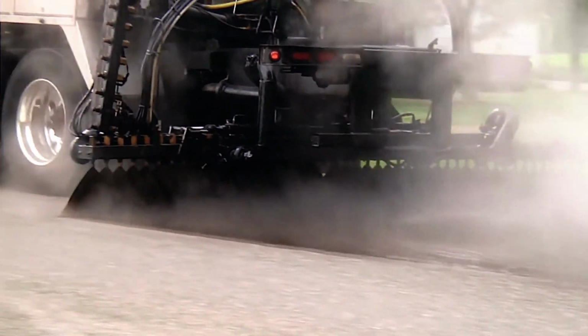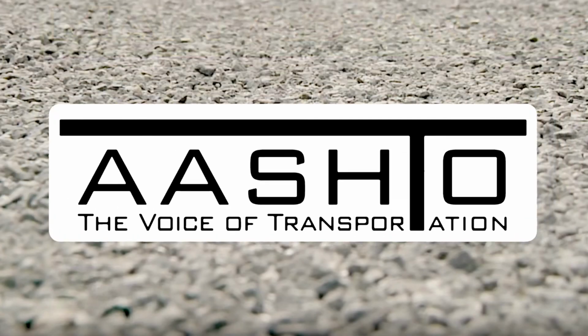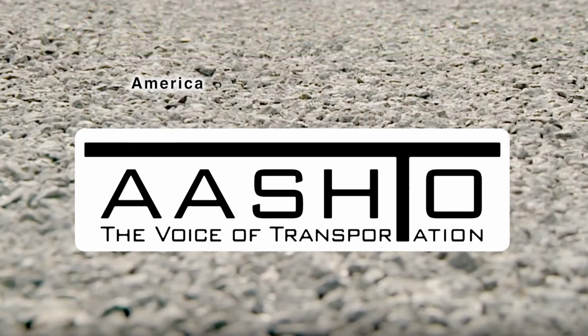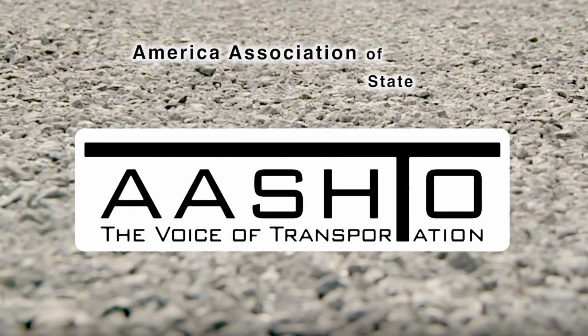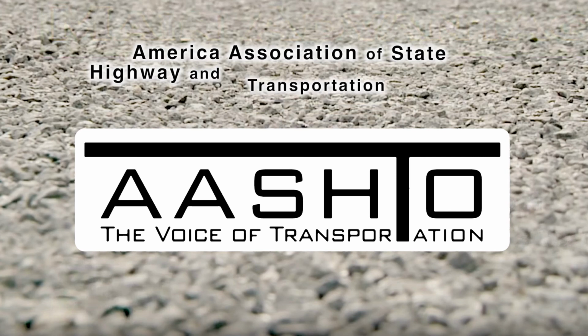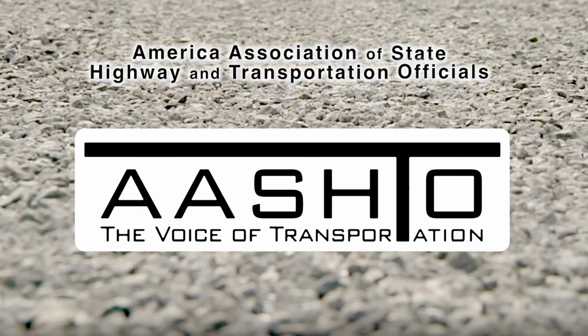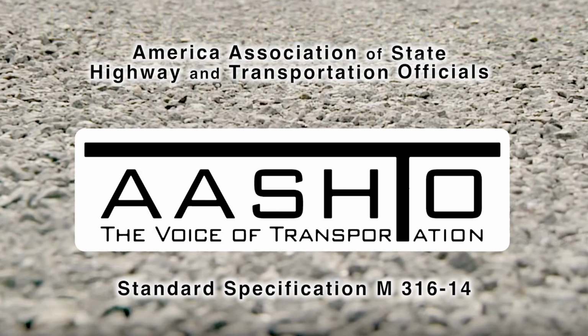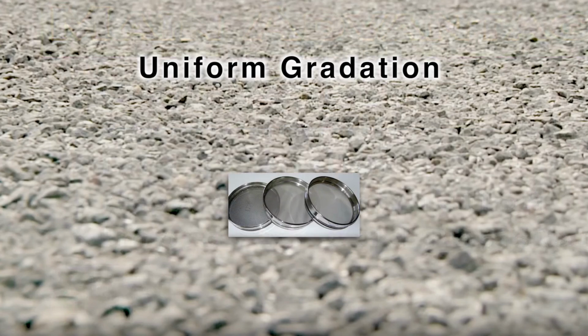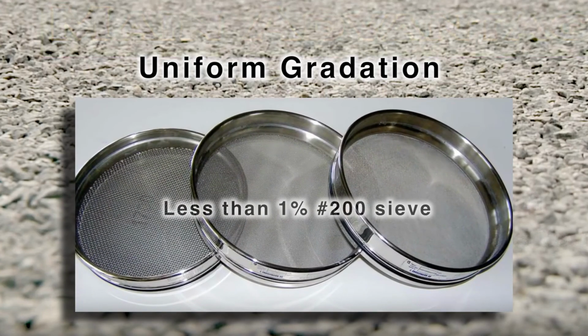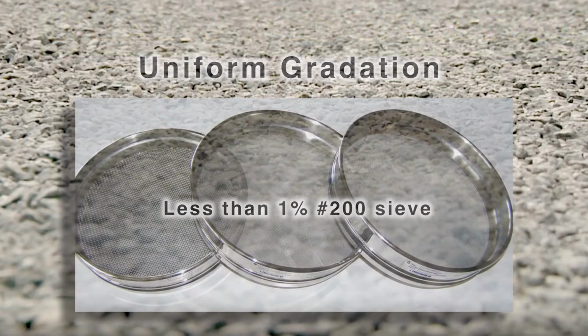The polymer-modified emulsified asphalt must comply with the requirements of the American Association of State Highway and Transportation Officials, Standard Specification M316-14, and must use a uniform gradation aggregate with less than 1% passing a number 200 sieve.